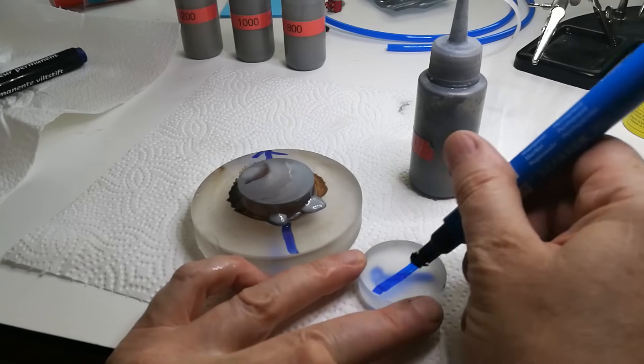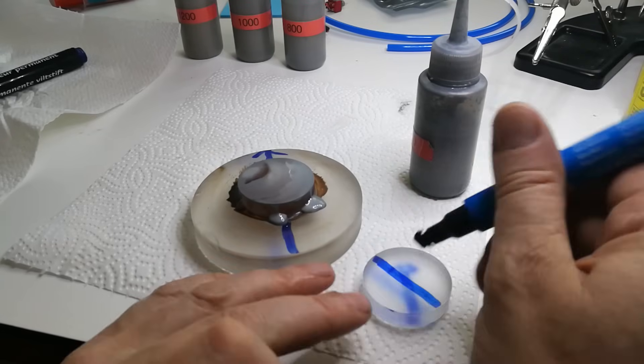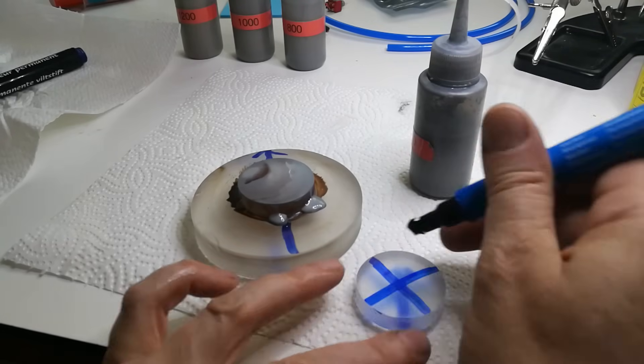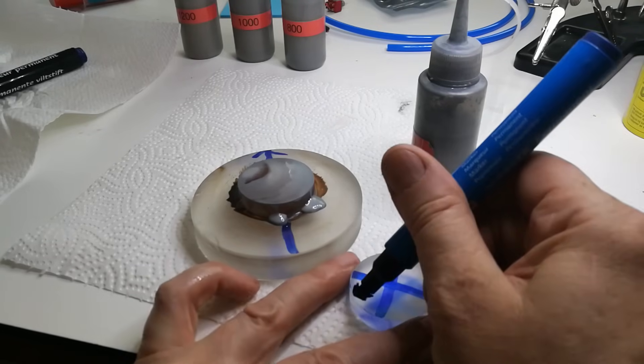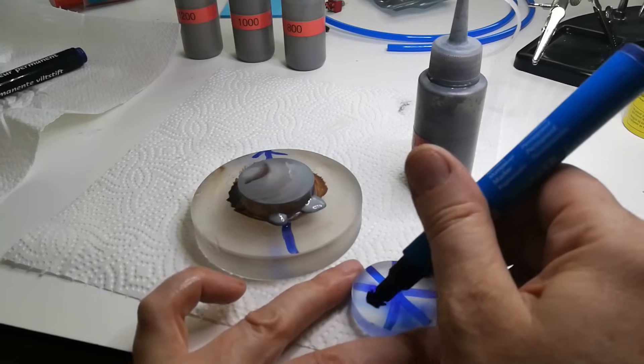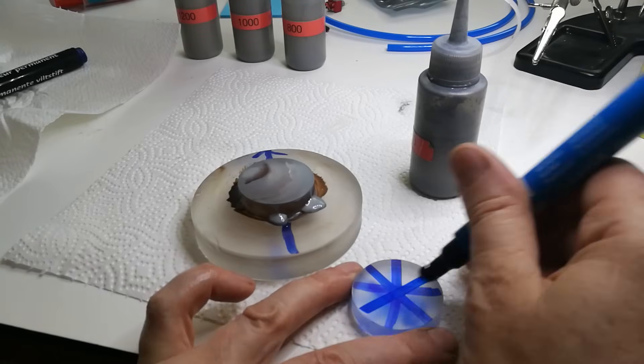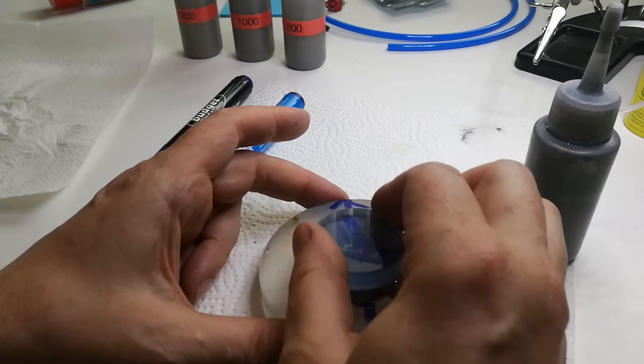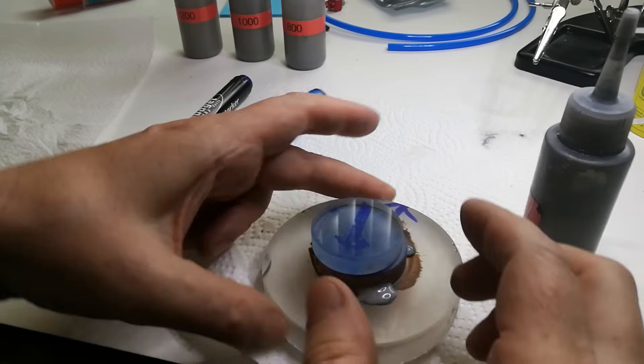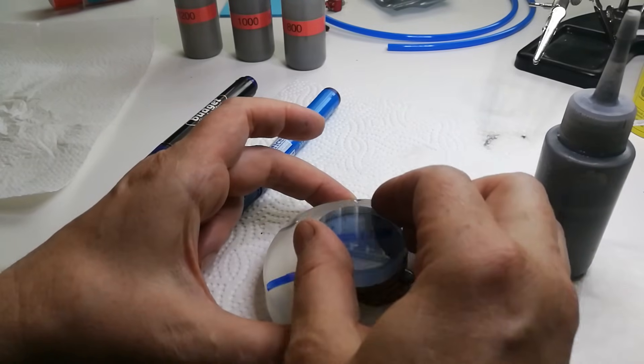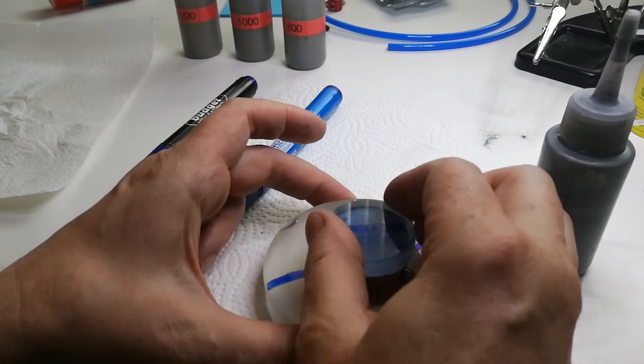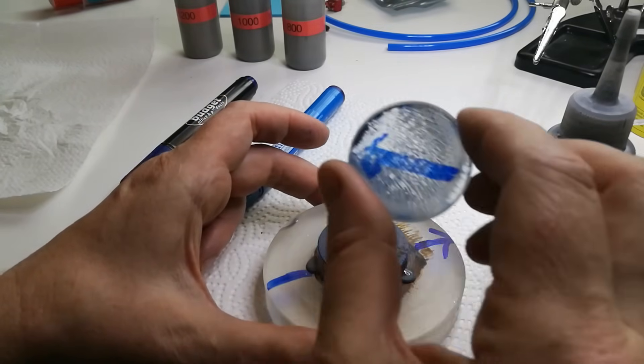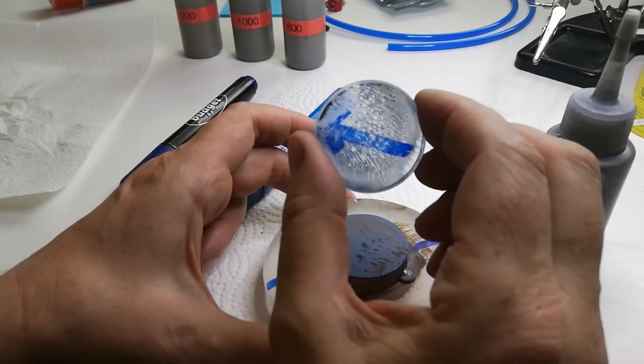Ok, back to our blank. To check if the shape of the surface is spherical, we can use a pencil or a permanent marker on the side where we grind. If the lines grind away uniformly over the whole surface, we know that there is good contact in all areas, which indicates a correct spherical shape.